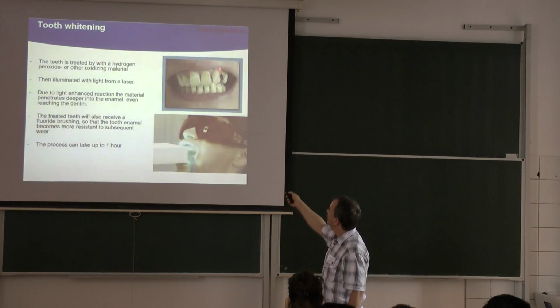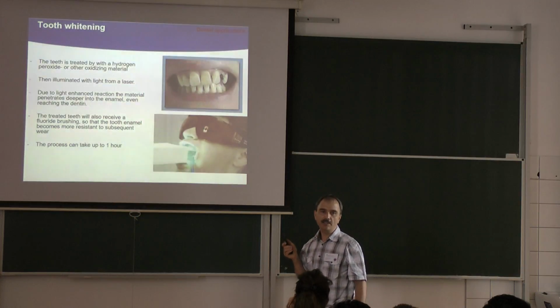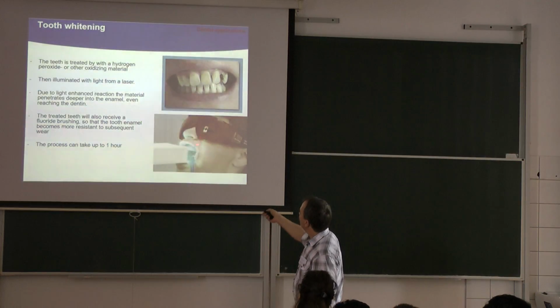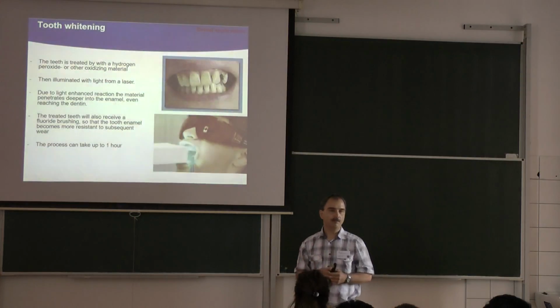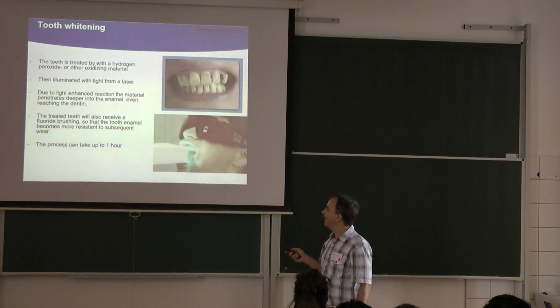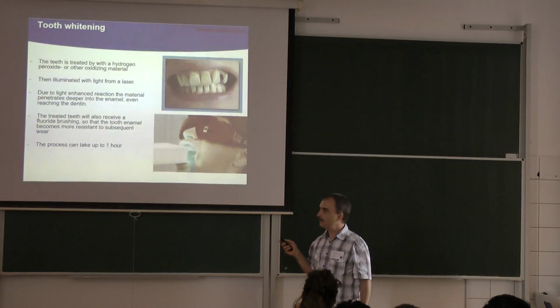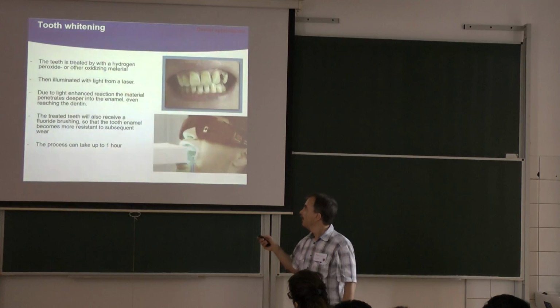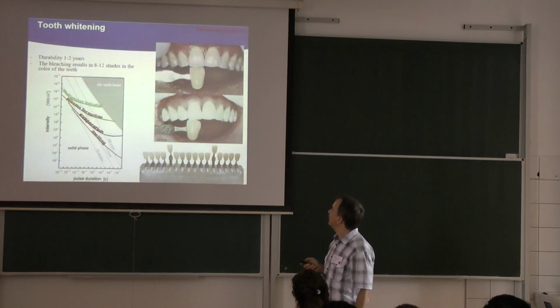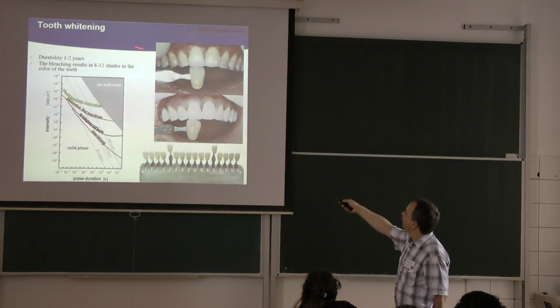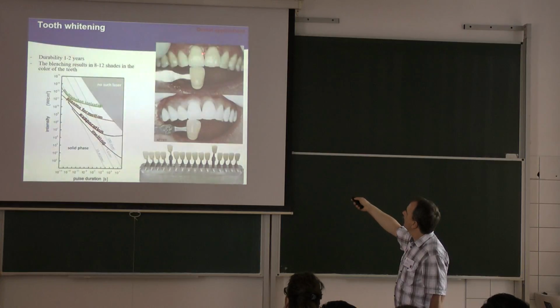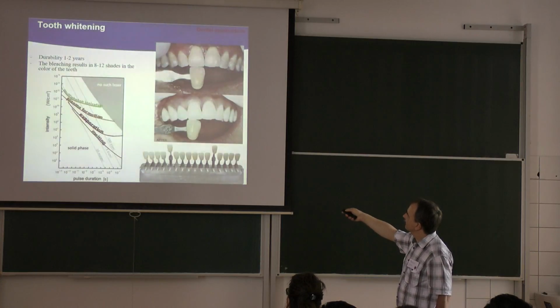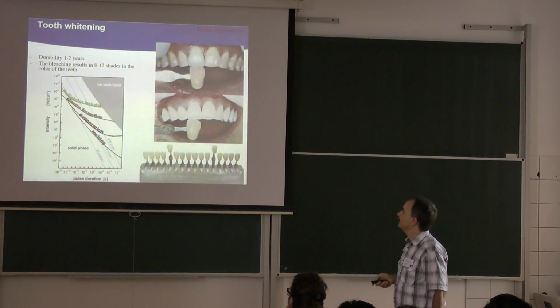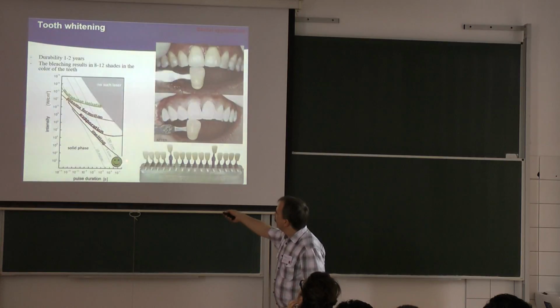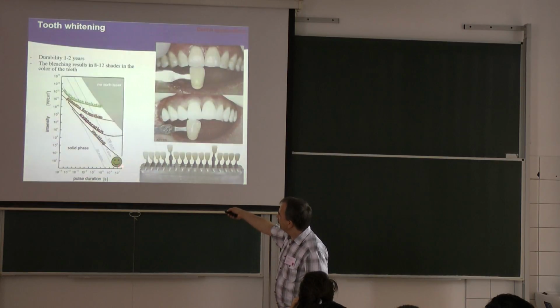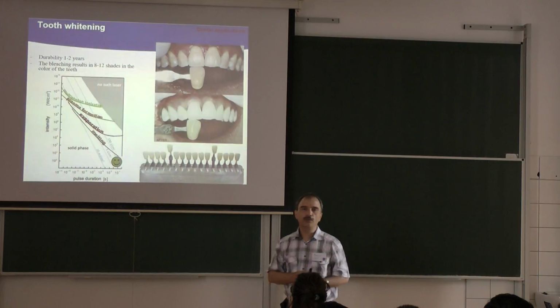And well, usually a professional tooth whitening takes an hour or even more. If we use lasers, we can enhance the speed by a factor of 2-3, which gives a better result. Or if we keep that 1 hour, then the result will be much nicer. So if you see the tooth whitening before and after, 8-12 shades can be obtained with this laser treatment. For this type of illumination, you use a long time and very little power, because you do not want to modify the tooth material.